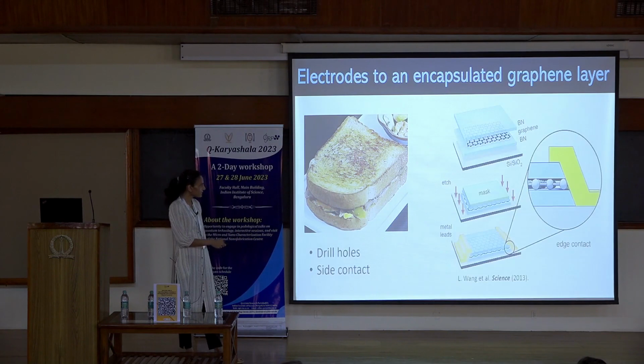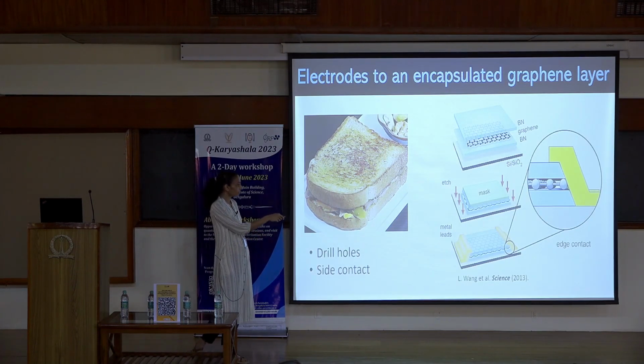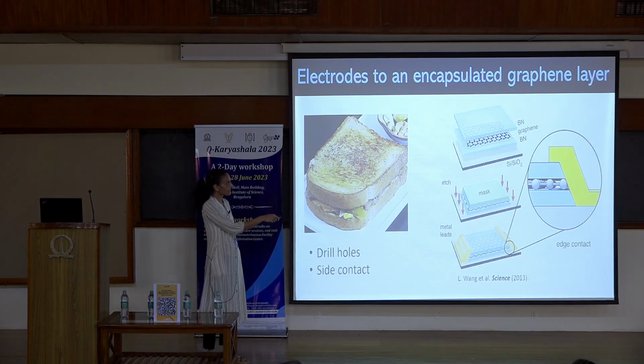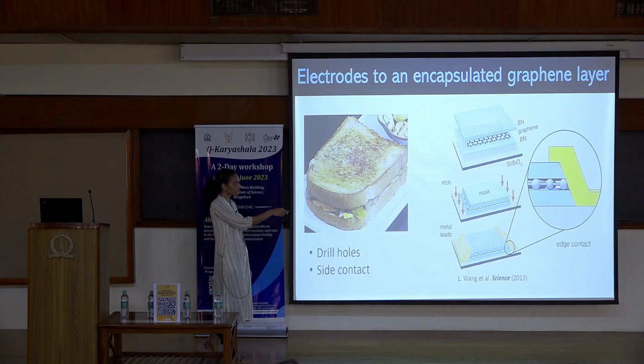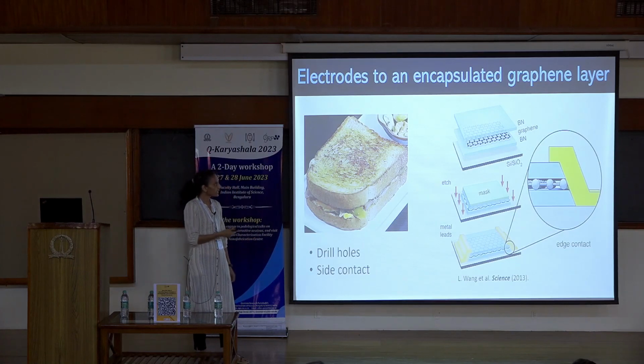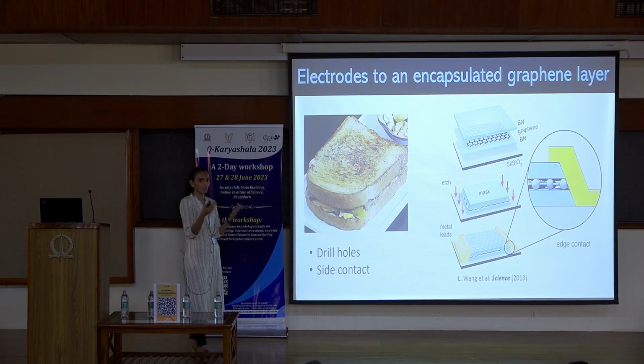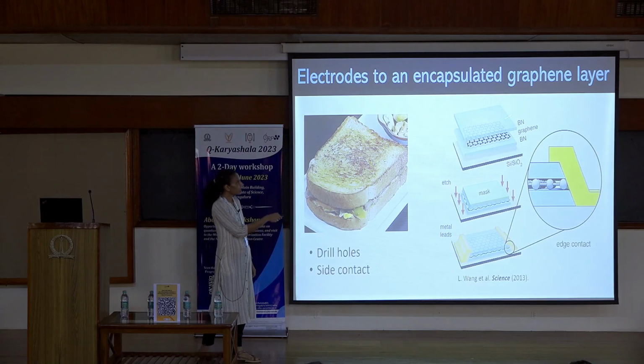What I mean by that is, this is a very interesting technique from this paper. This is what is being used currently the world over. Let's say that you have a boron nitride, graphene and a boron nitride. Now this is a typical structure, where graphene is encapsulated within 2 layers of boron nitride. Boron nitride is an insulator. This is a structure that gives you the highest quality electronic devices, mainly because this graphene would not see any outside residues, polymers or anything else that is needed to do the fabrication process that we are talking about. So this graphene is very clean, and that leads to the highest quality.